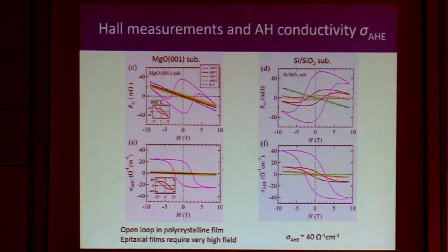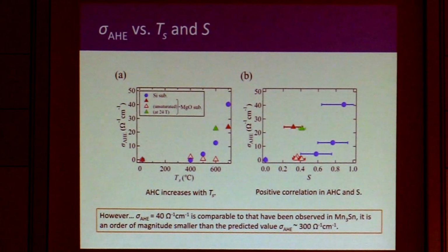So the epitaxial film actually requires a very high field to see the opening of the hysteresis loop. And of course, for the manganese 3 tin on the thermally oxidized silicon substrate, they are all polycrystalline. So we see a very nice hysteresis curve, and the anomalous Hall conductivity goes up to 40 inverse ohm centimeter. To summarize, we can see this anomalous Hall conductivity increase as we increase the substrate temperature, just ignoring this unsaturated value where we need a much higher external field.